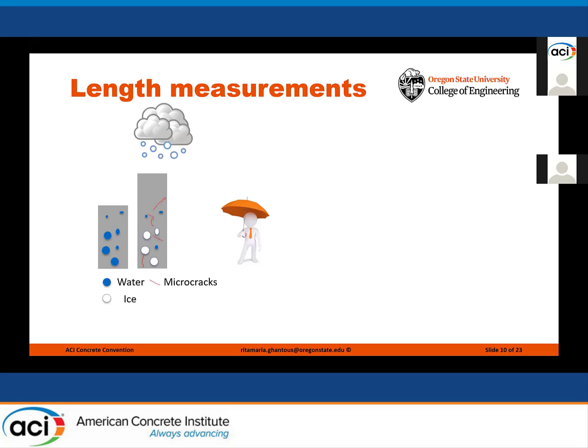So to start with the correlation of length change measurement with freezing and thawing damage, if we hypothesize that all the concrete pores are filled with water, when the temperature drops, some of the solution in these pores will freeze, especially the solution in the capillary pores and in the air voids. In addition, some microcracks will develop due to different pressures, osmotic, hydraulic, electrical, when the ice forms. And then due to the increase in the volume of solution with ice formation and due to these microcracks, the length of the sample will increase, as you can see in this schematic.